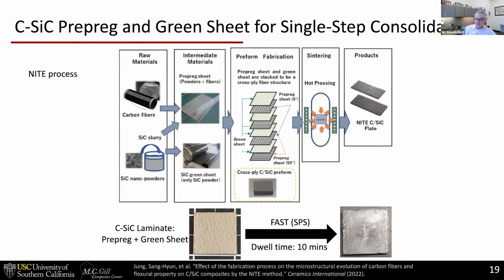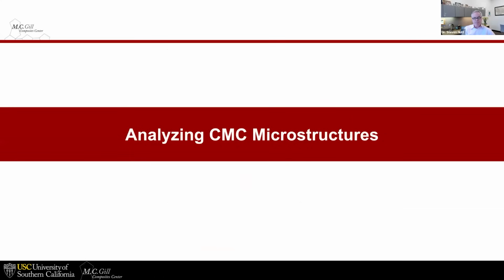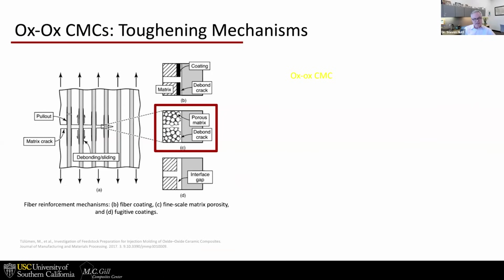Hot pressing is a relatively slow process, but well established and widely used, versus the FAST or SPS process, where you're talking about densification in a matter of minutes. And finally, I'll talk about analyzing CMC microstructures. Here's that well-traveled schematic that's showing the principle of fiber toughening by interface crack deflection.